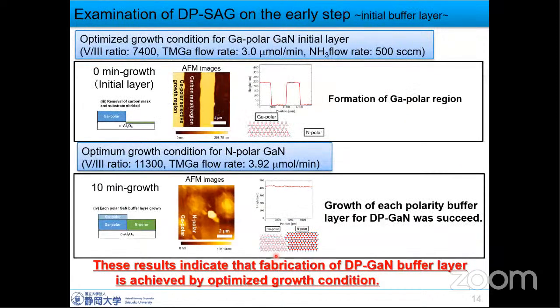In this slide, I'm talking about examination of DP-SAG on the early step. Following the AFM image of the gallium initial layer, a gallium polar region was fabricated on the unmasked region, and no layer was grown on the carbon mask region.